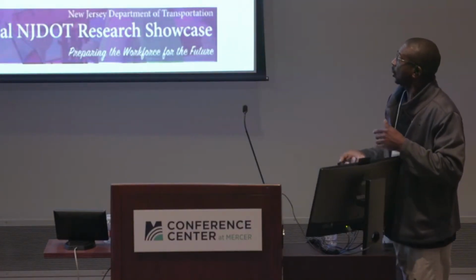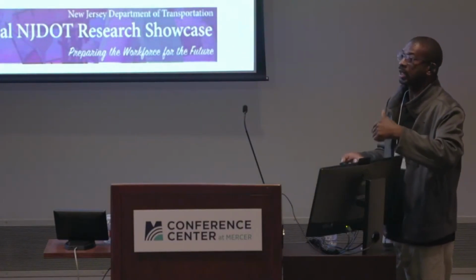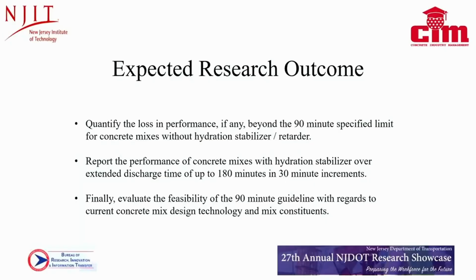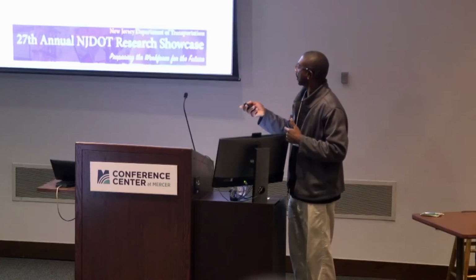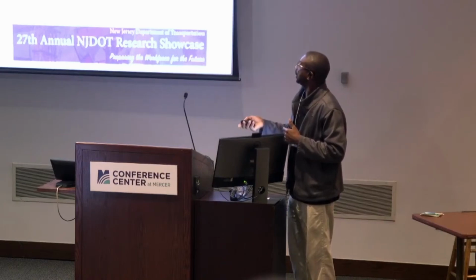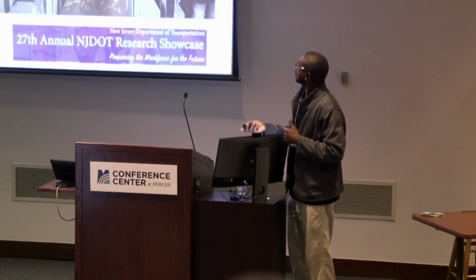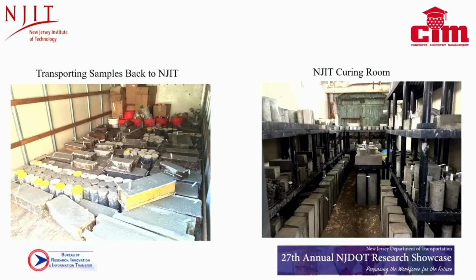What we found is that for the 100% cement, we had to redose about every 30 minutes, and for the cementitious materials with the fly ash and slag, we had to redose about every 90 minutes, right? Of note, no additional water was added. The hydration stabilizer, if we were using it, was introduced at the beginning of the mix. And after that, the only time the mix was tempered was with high range water reducer and air entrainment admixture if necessary. So here we have the specimens.